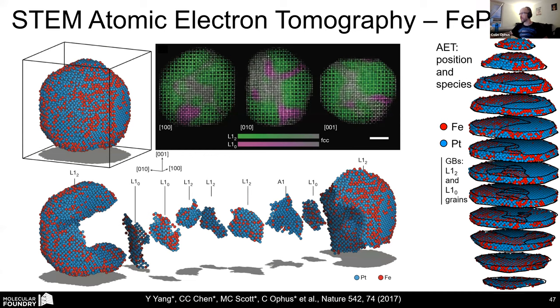A lot of my group's work is to pull apart these data sets and then measure things like the local internal grain stacking, chemistry, what have you, of these materials. But there's a problem. The imaging method that we use for all of these studies, high angle annular dark field, is an incoherent method, very dose inefficient. So I already showed you at the beginning of the talk that ptychography can do better.